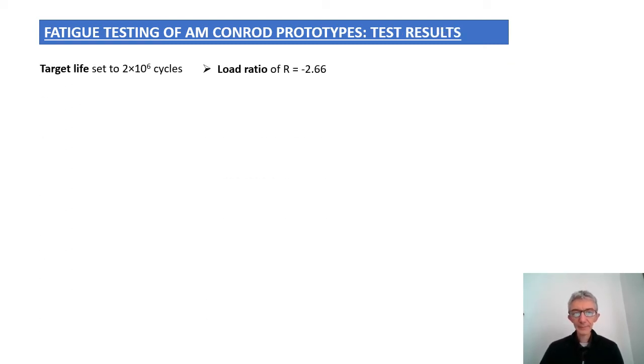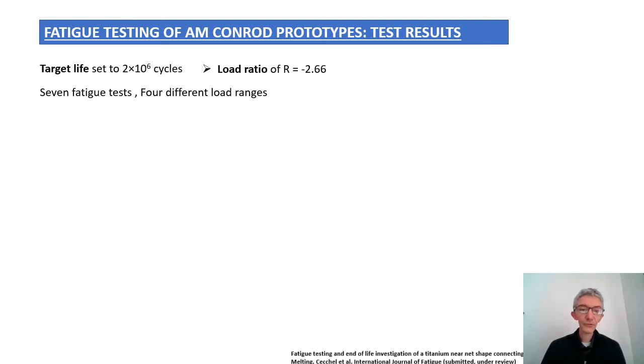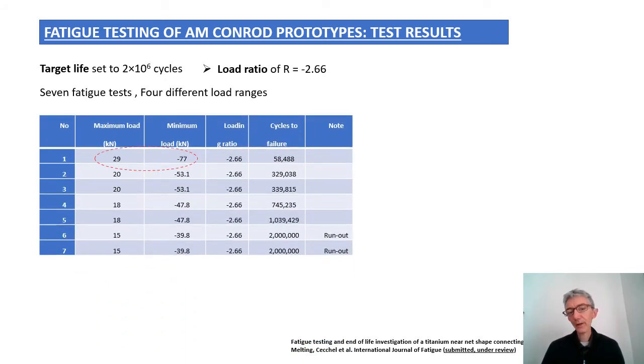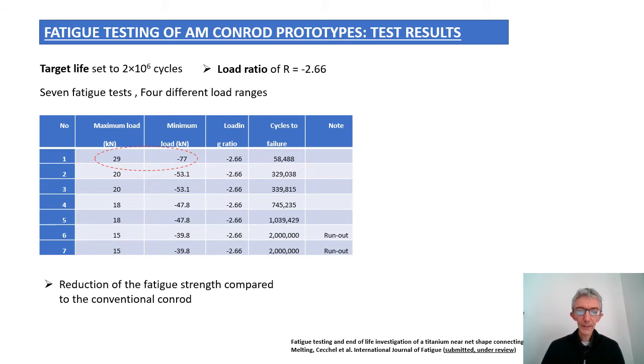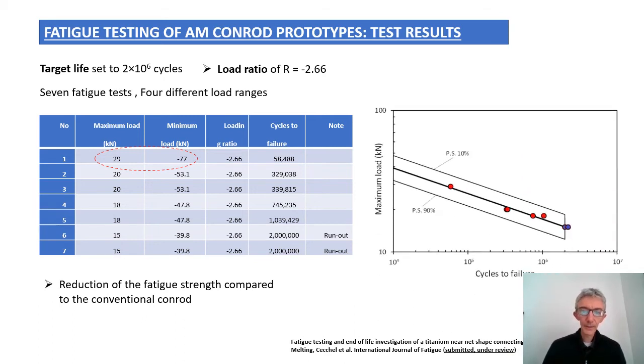In terms of results, we carried out tests with a target life of 2 million cycles, a load ratio of R equal to minus 2.66. A total of 7 fatigue tests was carried out within 4 different load ranges. And the first result is that for the higher load level, a reduction of fatigue strength of this new solution was observed in comparison with the conventional conrod.